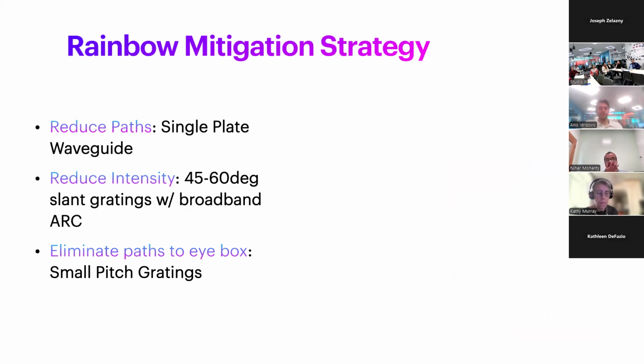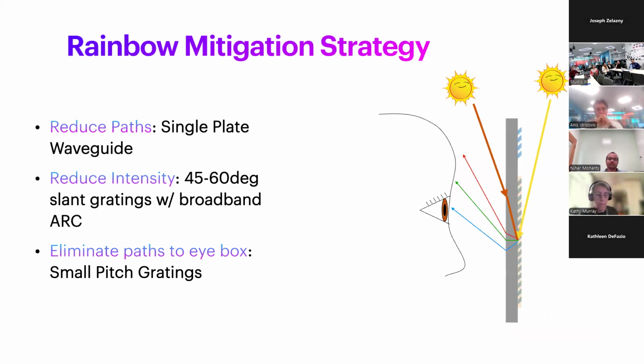And this is where we had our final path. This starts with a simple premise, which is to eliminate the rainbow paths to the eye box. One way to achieve this is with smaller pitch gratings, which pushes the diffraction angles of the light to steeper angles and hence misses the eye box. While arbitrarily smaller pitch could technically eliminate all rainbow paths to the eye box, it is not practical due to the need to maintain high display path efficiencies. The typical optimized pitch for silicon carbide based on single plate waveguide cuts most of the red and green paths with some faint blue paths remaining. This is an optimum scenario because our retinal receptors have much lower detection efficacy for blue light.